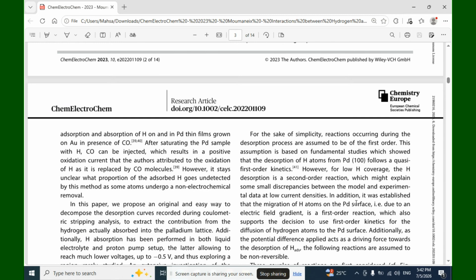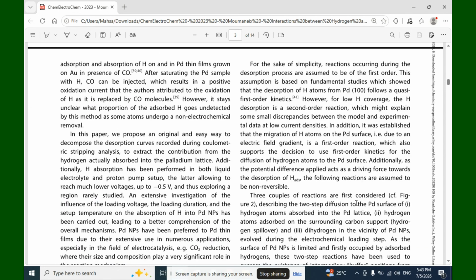However, it stays unclear what proportion of the absorbed hydrogen goes undetected by this method, as some atoms undergo a non-electrochemical removal. In this paper, we propose an original and easy way to decompose the desorption curves recorded during the coulometric stripping analysis to extract the contribution from the hydrogen actually absorbed into the palladium lattice. Additionally, hydrogen absorption has been performed in both liquid electrolyte and proton pump setup, the latter allowing it to reach a much lower voltage, up to minus 0.5 volt, and thus exploring a region rarely studied.